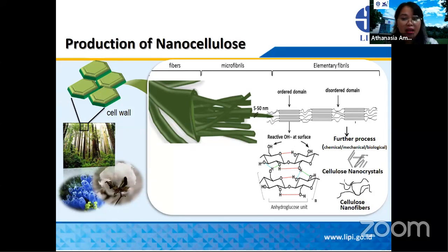And if we apply several processes such as chemical, mechanical, biological, we then can obtain controlled structure nanocellulose, which is in the form of the cellulose nanocrystal, as well as the cellulose nanofiber as the dominant form of the nanocellulose.